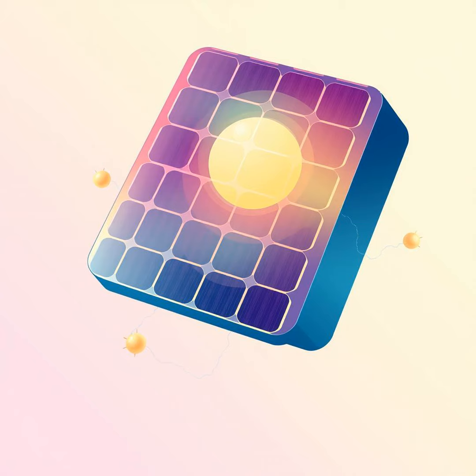The numbers here are really impressive. They took their improved method and fabricated a large mini-module with an aperture area of almost 50 square centimeters. This isn't a tiny laboratory cell. This is a real-world-sized device, and it achieved 23.15% efficiency. Now here's the critical part. When you scale up solar cells from laboratory size to larger modules, you usually lose performance. It's called the scaling bottleneck, and it's been one of the biggest hurdles preventing perovskites from moving into commercial production. But with this new method, the efficiency drop was less than 3%. That's remarkable. That's production-ready remarkable.